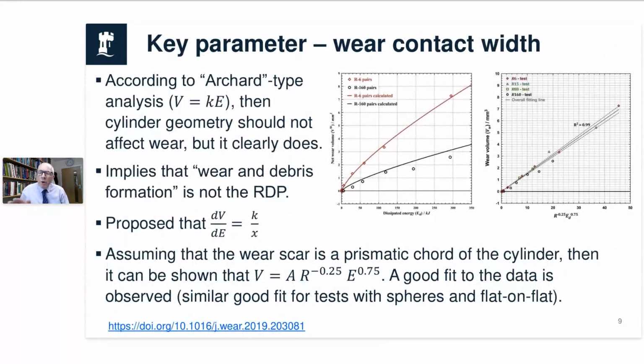And what we were able to do, sorry, let me flick back. What we were able to do then was to show with the figure on the right-hand side, when we plotted the wear volume versus R to the minus 0.25, E to the 0.75, all of the data fell onto a straight line. And we did that with 6mm cylinders, 15mm cylinders, 80mm cylinders, and 160mm cylinders. And we've also applied it to work of others where they've done work on sphere on flat, and we've demonstrated through a variety of places that this holds good, this concept that the wear depends pretty critically on the size of the contacts. So that means that just applying Archard is not appropriate.